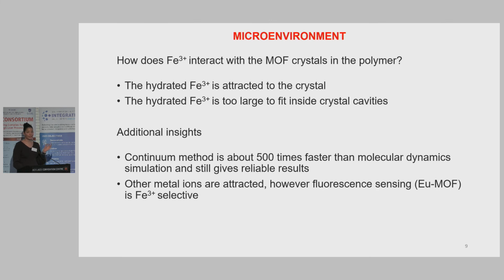We found out iron 3 is attracted to the MOF crystal, however, it's too large to fit inside the cavities. This isn't bad news. This is actually good news, because this means that we can reuse the sensor, and this is a cost saving. Some additional insights is that we found out our method is about 500 times faster than molecular dynamics and still provides reliable results. We also found that the other metal ions are attracted to this crystal, but this crystal in particular is iron 3 selective in terms of sensing.